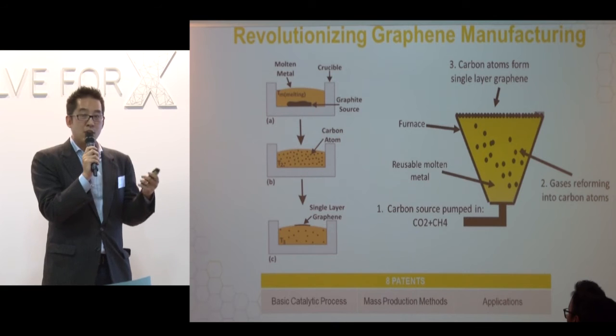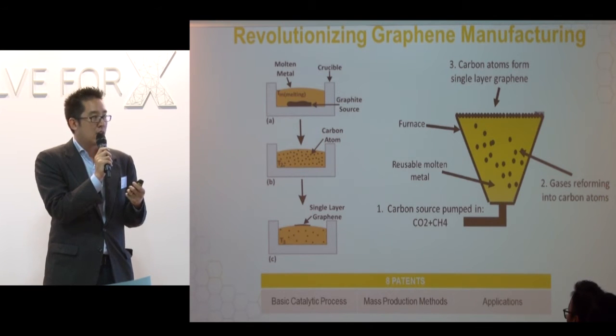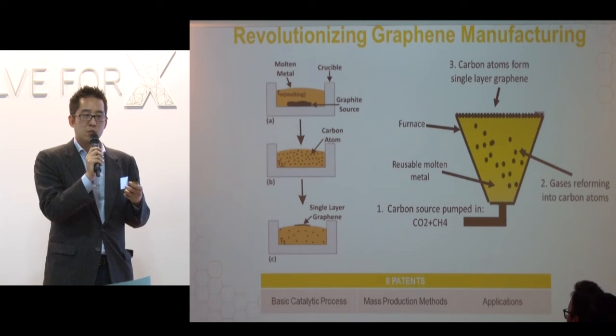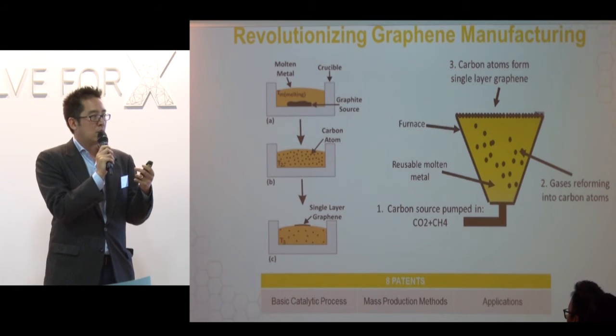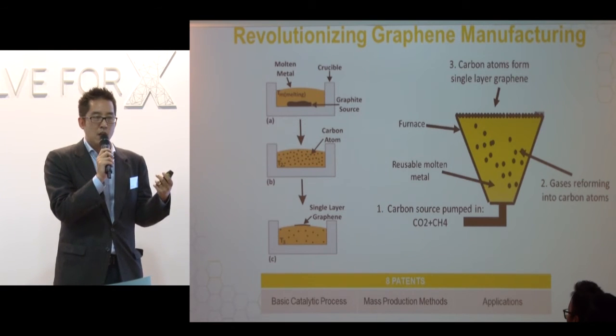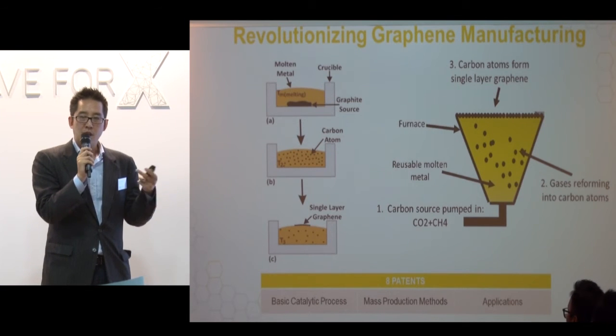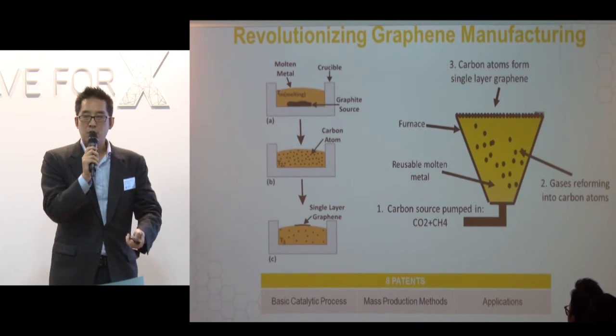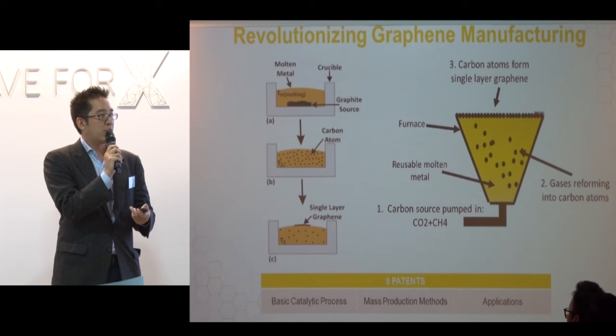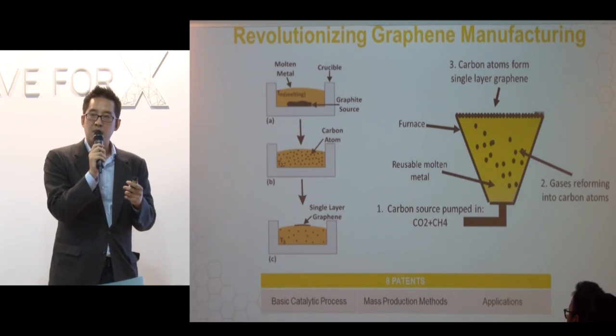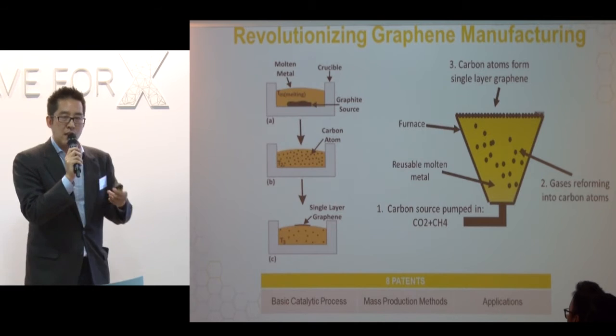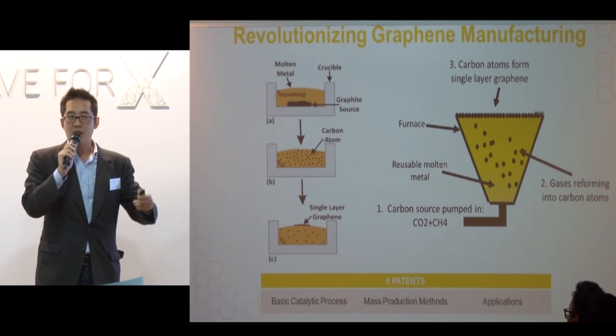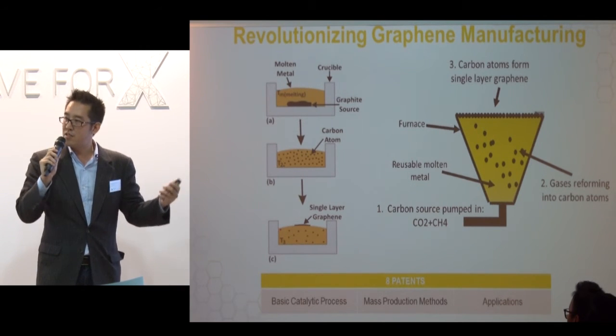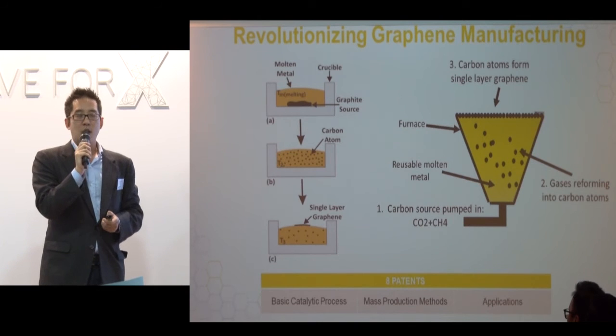We're using iron, what we call pig iron, and in making steels, we're trying to cook out the carbon to create a high-quality steel. We're essentially doing the reverse process. Instead of cooking out the carbon, we're supersaturating the metal solvent with carbon, and that carbon reprecipitates as graphene. But we can leverage the same huge industrial furnaces, the same equipment that produces tons of steel, to create graphene.